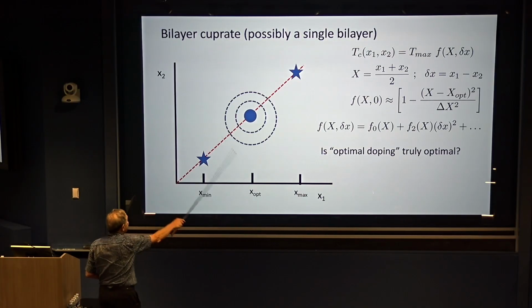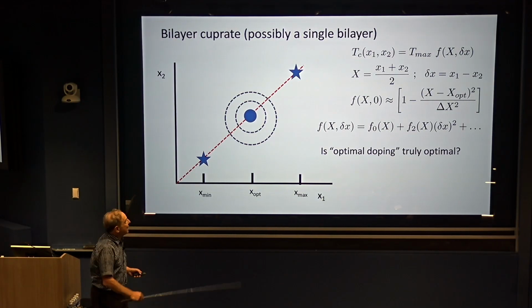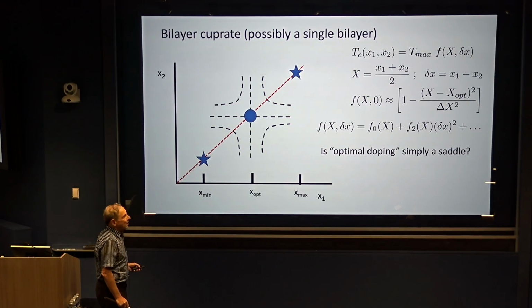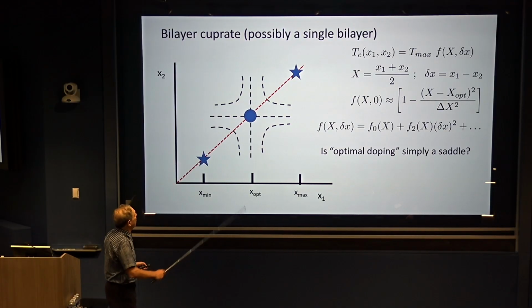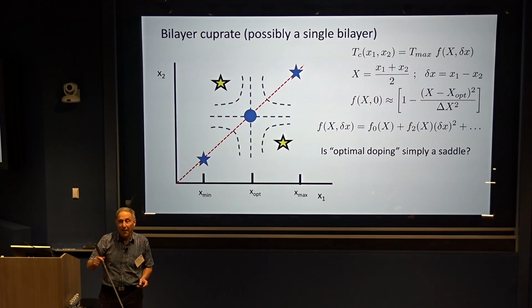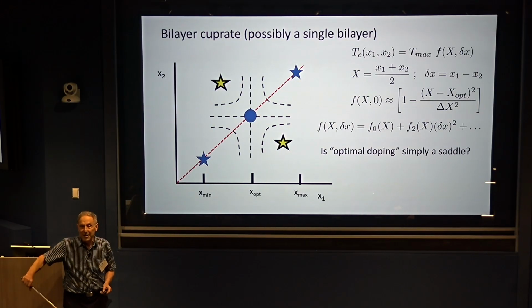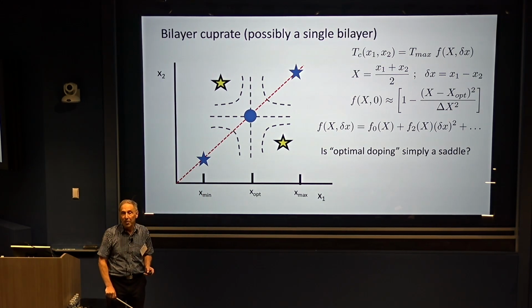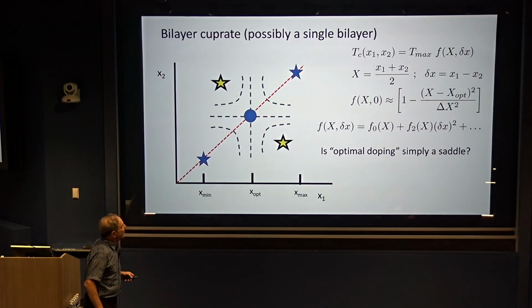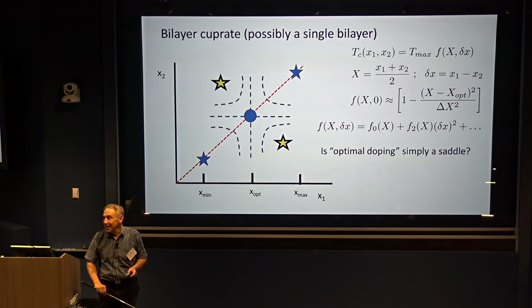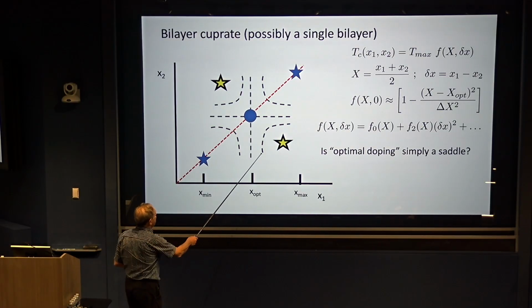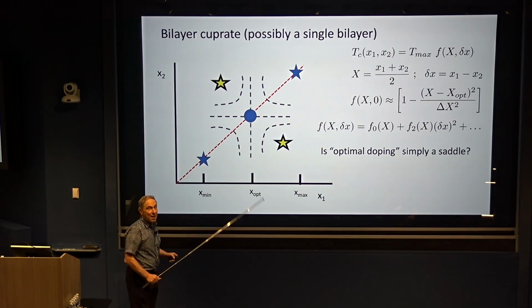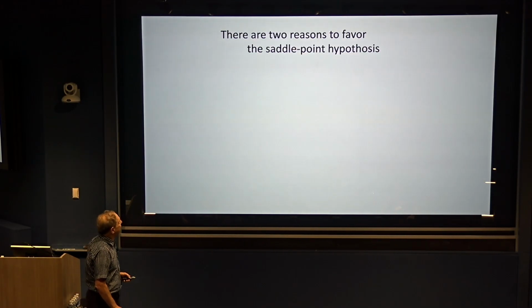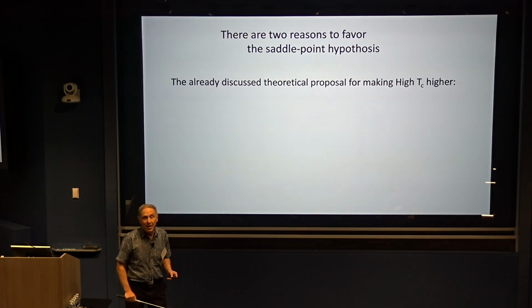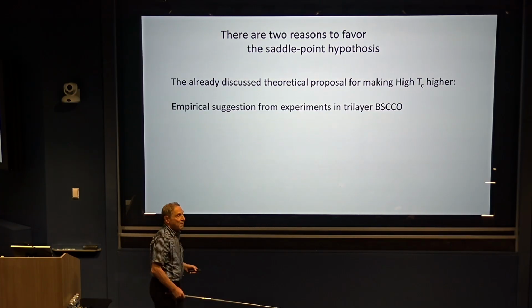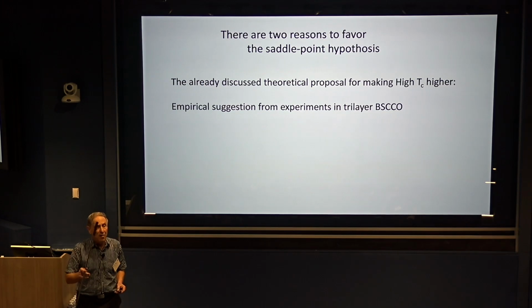And as you move off, I mean, it must be symmetric as I move off of here, but it could be a mountaintop like this, or it could be a saddle point like that. And if it's a saddle point like that, then somewhere out here, we would find the optimal TC in this two-dimensional phase diagram, which could be substantially bigger than the optimal TC we found so far. So that's just on functional analysis. These are the two possibilities with a 50-50 chance of one or the other. But with the motivation that I've just described, we might think that it's a good chance that this is the case that applies. Okay, so that experiment hasn't been done, but there are very suggestive experimental results from trilayer BSCCO.